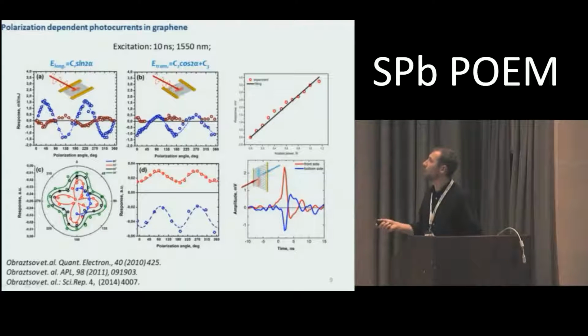So first we were able to obtain polarization-sensitive photocurrents, which we relate to photon drag in graphene. These photocurrents demonstrate very nice, very pronounced dependence on polarization of excitation. And as I said previously, these photocurrents are sensitive to the k vector. So by shining our sample from one side or the other side, we can produce photocurrent of opposite polarity.